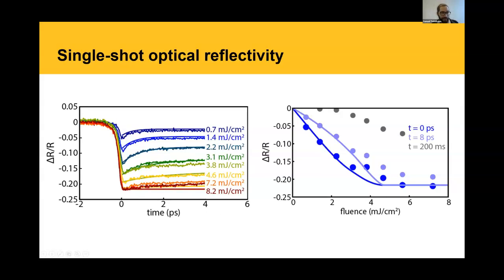And the reason the static reflectivity saturates is because you can't melt more than 100% of the charge. And what we can do is we can connect this switching threshold at 2.2 millijoule per square centimeter to the total amount of charge order melting. So essentially at 8 millijoule per square centimeter, you're melting 100% of your charge order, which is this reflectivity change here. And at the switching threshold, you're melting about 1/2 to 3/4 of the charge order. And this will become important later. So in order to understand and quantify this more deeply, so now we know that we're melting the charge order, and that if we melt about 1/2 to 3/4 of the charge order, we can begin to photo switch.